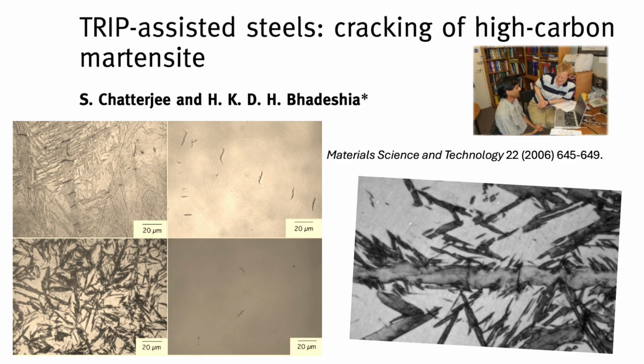For instance, austenite transforming to martensite in a steel with, say, 1% carbon causes a volume increase of about 4%. A 4% increase inside a solid piece of steel. That sounds problematic. It is. Imagine parts of the steel suddenly trying to expand while locked inside the surrounding material. Even transforming to pearlite involves about a 2.4% increase. It creates massive internal stress.